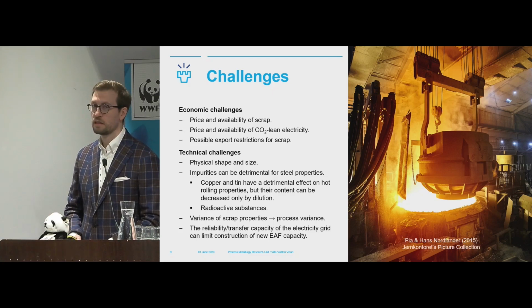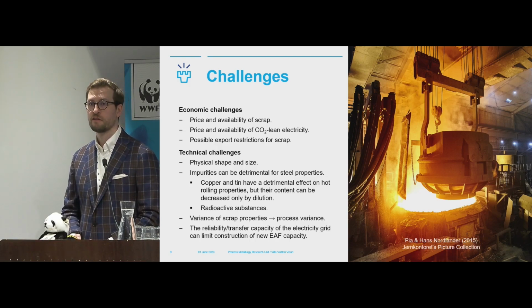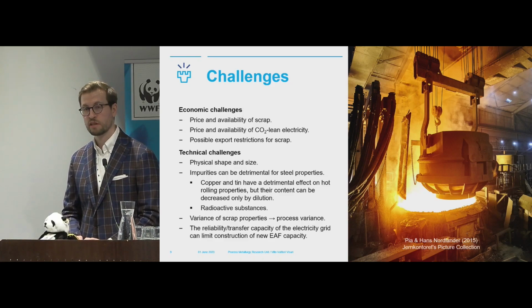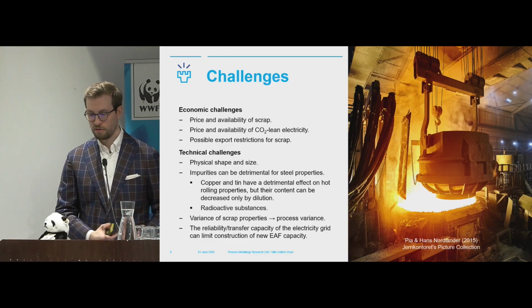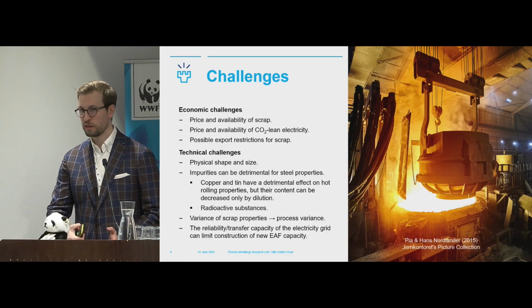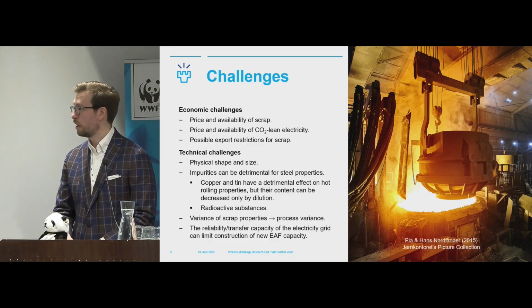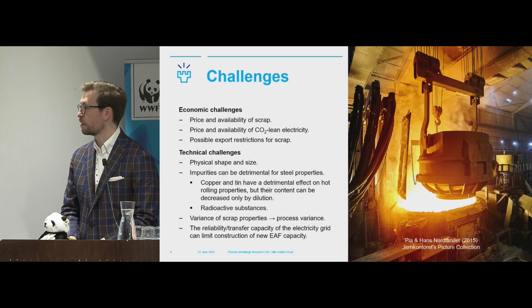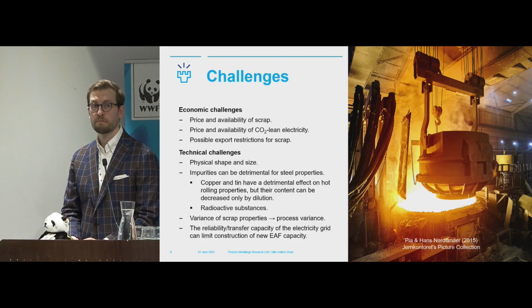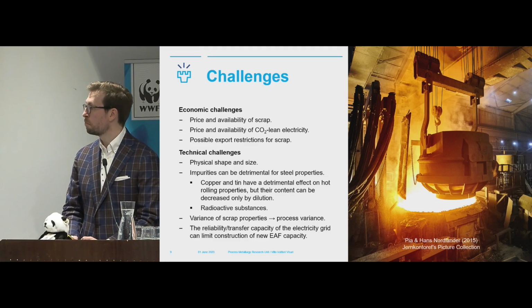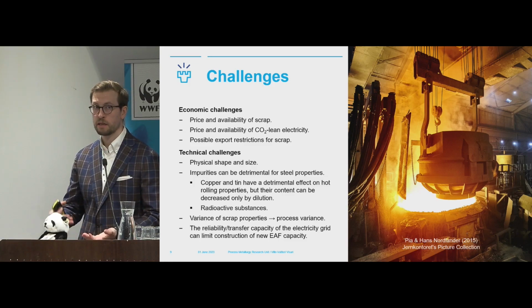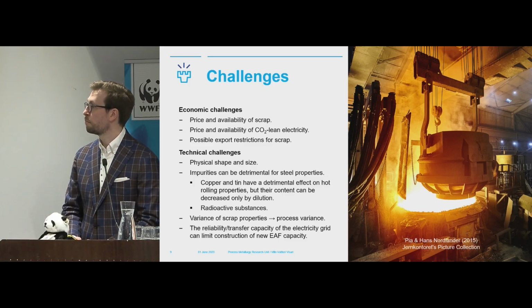Then there are radioactive substances which are a great pain in the steelwork because it's simply not allowed. Then you have variance of scrap properties. It's very difficult to control the electric arc furnace process if you don't know your inputs. And this is really the case that when we are trying to simulate the electric arc furnace process, we have a lot of unknowns. We don't really know what goes in, so it's relatively difficult to predict accurately what comes out. And this is something that we need to address using better scrap sorting, better analysis of scrap, and probably that then adds value also to the product when it's being sorted better, let's say.